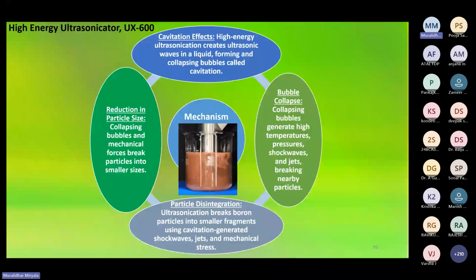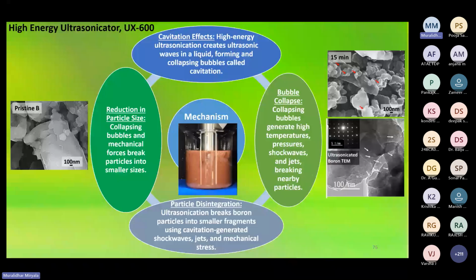When you use the cavitation effect, high energy ultrasonification creates ultrasonic waves in the liquid, forming and collapsing bubbles, called cavitation. During this process it generates high temperatures and pressure, shock waves and jets. When these jets and powerful waves are created and the boron particle comes around there, it will automatically break. And this process runs continuously. One can make nanoboron that is very pure, and one can make very small sizes up to date.